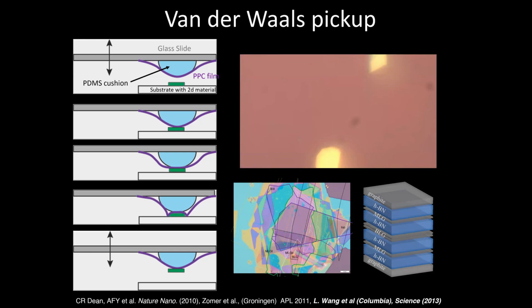So here's a heterostructure that we made for reasons I won't get into with a lot of layers. And you can see you can use a graphite, and then a boron nitride, and then a monolayer of graphene, and then another boron nitride, and a bilayer, and a boron nitride, and a monolayer, and a boron nitride, and so on and so forth, right? And you can do all of this, again, like pretty easily. You can train an undergrad to do this in a couple of weeks.